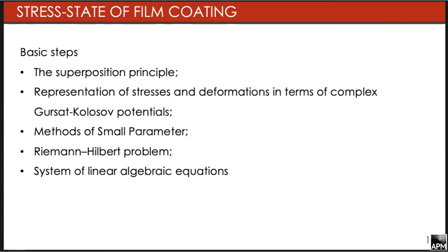To solve the problem of joint deformation of the film with the substrate, I use the approach proposed by Mikhail Grekov. I will describe it very briefly. First, using the superposition principle, the solution of the initial boundary value problem is represented as the sum of the solutions of two simpler problems. In the first problem, the deformation of a half plane with a curved boundary is considered. In the second problem, the deformation of a two-phase plane with a rectilinear interface is considered. To solve these problems, we use small parameter methods.